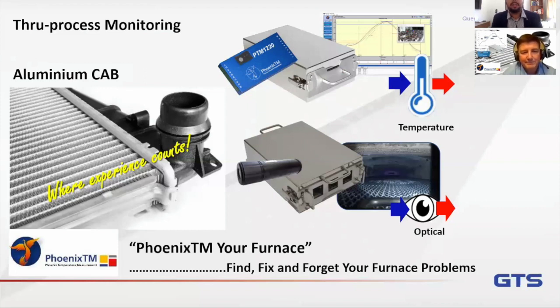You probably have seen a lot of this, Steve. Yes. I don't think I've seen an example in brazing, but in other heat treatment applications, you've obviously got to also consider what's the starting point of your product temperature. If you've got products that have been stacked up in a warehouse or a factory environment in winter for any length of time, their ambient temperature will be of a set temperature in line with the conditions inside the storage facility. And therefore, you may have a product temperature swing of maybe 5 to 10 degrees between winter and summer. Now, you've got to take that into account, that you're putting a lot of metal possibly inside your furnace at a cooler temperature than you would do in the summer. And that will have a knock-on effect on how efficient the furnace is working, because the furnace has to heat that product up through a further 5 or 10 degrees to get to the optimal temperature you need for your particular heat treatment.